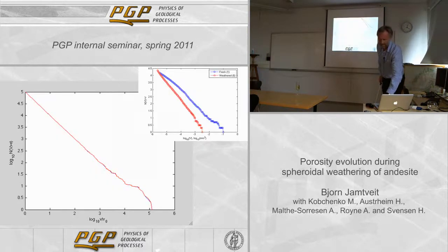Because we see Liesegang banding, we could expect that we have a significant threshold of nucleation, so that we need quite a lot of supersaturation before things nucleate. And because nucleation is heterogeneous in these rocks, it's not nucleation in a fluid, probably it's growing on the walls and nucleating on the walls. Then a big pore has more area than a small pore, so the likelihood of forming a nucleus in a big pore is bigger than in a small pore.